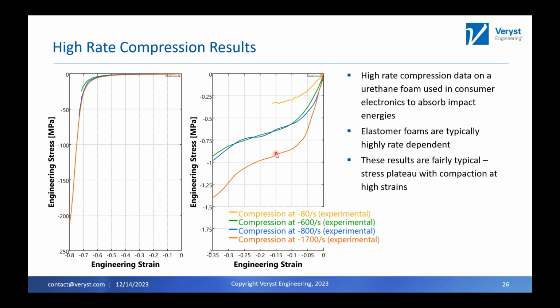If we look at 15% strain, we're up here near 1. We were down here near 0.6. And then we're all the way down here at maybe 0.3. So in a couple of decades of strain rate, you're seeing almost a 10x increase in the stress that you would expect at 10 to 15% strain. And so the rate dependence here is important.